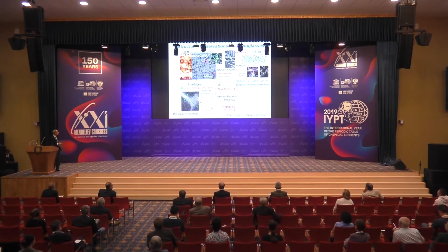And then, of course, we looked a little bit more into this and tried to find out why this is a ferromagnetic state. And what turns out, I'll just show you one result. In these interfaces, this is for iron 90 scandium 10, we see a very high density of BCC clusters. You can probably see them as bright spots here. So the interfaces are not uniform, but they consist of BCC clusters. BCC is a structure you get when you crystallize the material, and this is a cluster with the size of one elementary cell. And these elementary cells are separated by isolated atoms from each other.